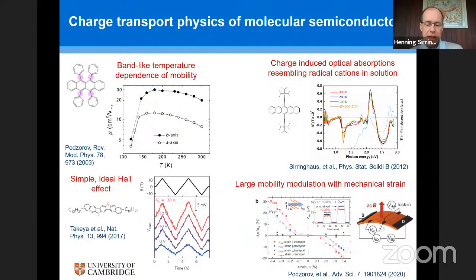And so experimentalists have then looked at the transport properties of these molecular crystals. And on this slide, I show you a few of the key characteristics that you typically observe when you're studying transport in these molecular systems. On the top left, you can see the temperature dependence of the mobility in one of the most widely studied molecular crystals called rubrene. And what you see there is that the room temperature mobility is on the order of 10 or 20. And as you then cool down, the mobility increases slightly and reaches a maximum around 200 Kelvin before it then drops sharply to lower temperatures.